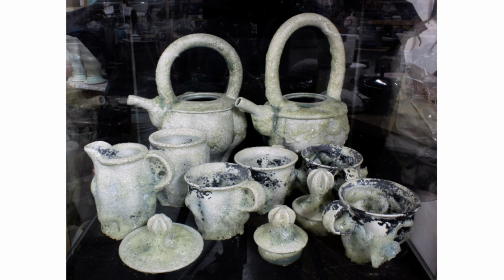And then don't dismiss the kiln god or goddess who just loves to play with your head—meaning stuff happens. These were fired in a soda kiln, and this happened one month before my MFA show at Alfred. It was quite a freak out, actually. We never found out what really caused the glazes to froth or foam, as shown here. I should have exhibited this in my show, but I didn't.